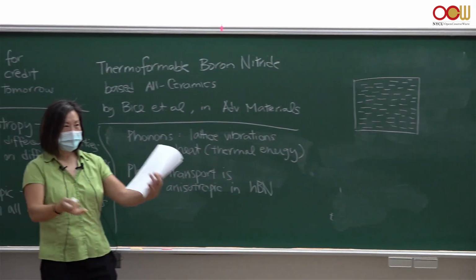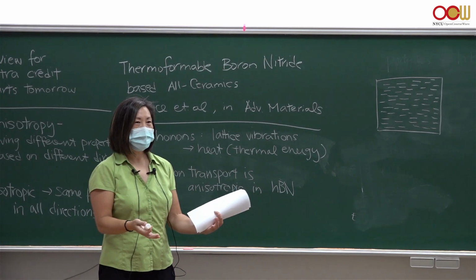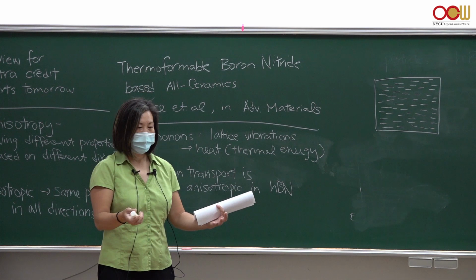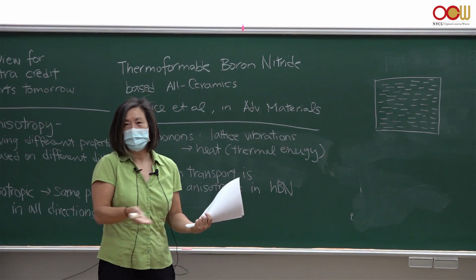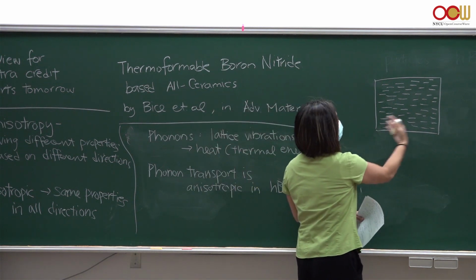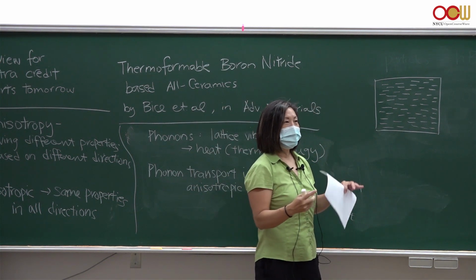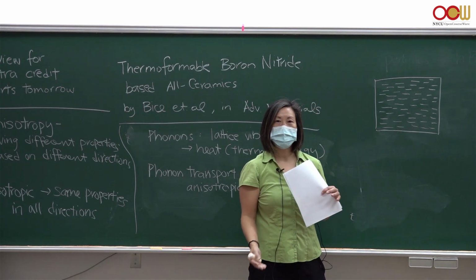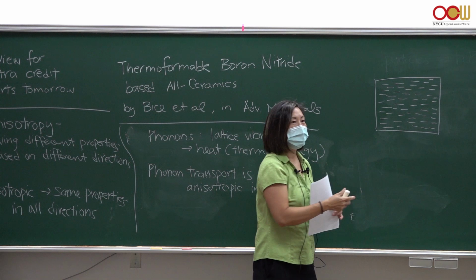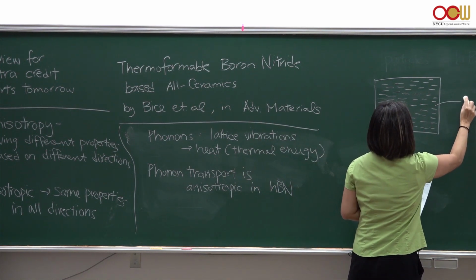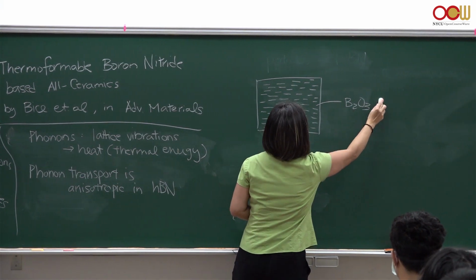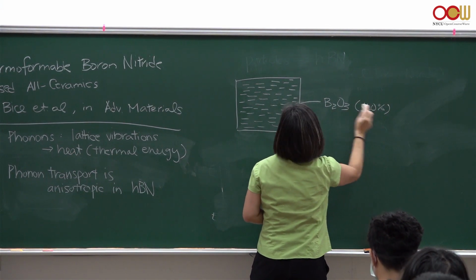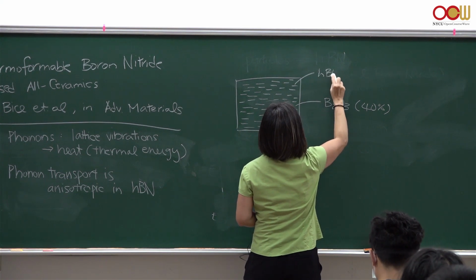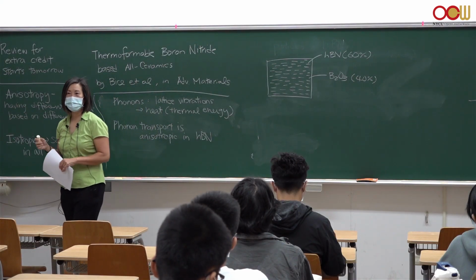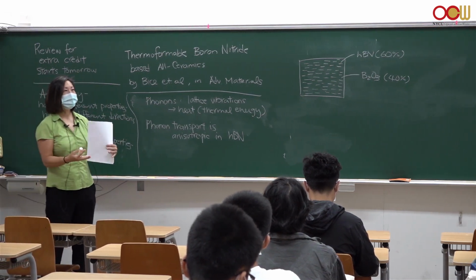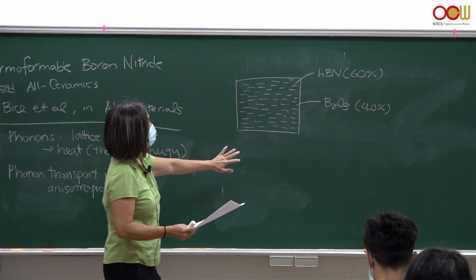So they take this boron nitride particle, they put it into a polymer slurry liquid, and then they shook it until everything is all lined up. And then they burnt off the polymer, and then they flow oxygen over this material, and it's replacing the polymer with a boron oxide. So the matrix ends up being B2O3, and this occupies 40% of the volume, and these particles are hexagonal boron nitride, and it occupies 60% of the volume. So there's a lot of particles packed into that matrix. So this is what they made.